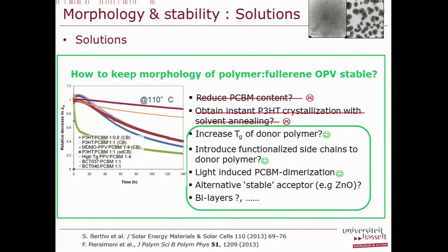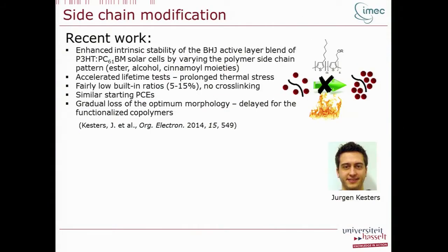We've seen that by increasing the glass transition temperature of the polymer, the donor polymer, we really had a dramatic increase of the stability. Also, many years ago, we started with introducing functionalized side chains to the donor polymer. Also, this was quite a successful approach. I just mentioned the light-induced PCBM dimerization, and then we looked also to other approaches. What I would like to do now is to show some further recent results on this sidechain modification.